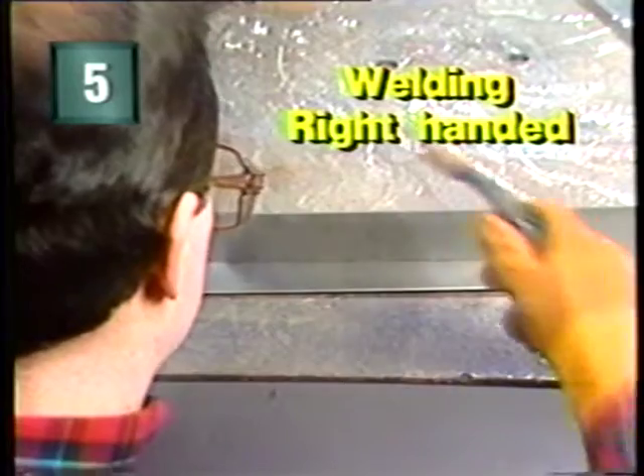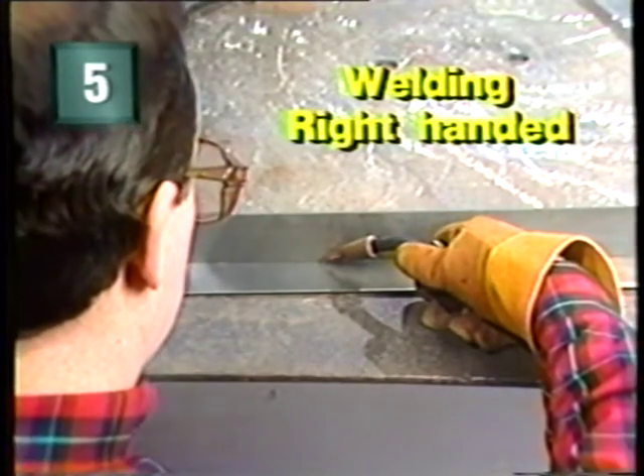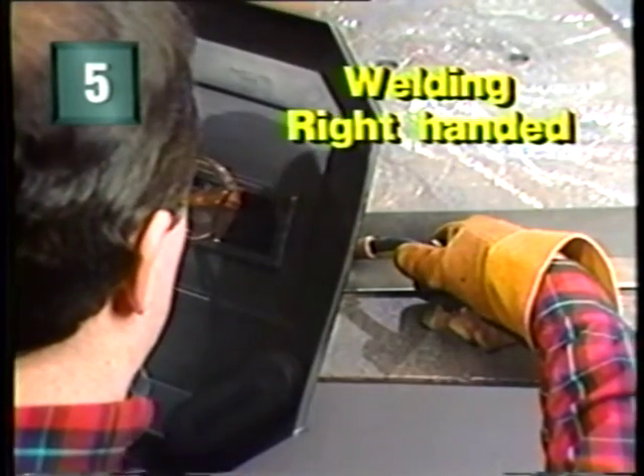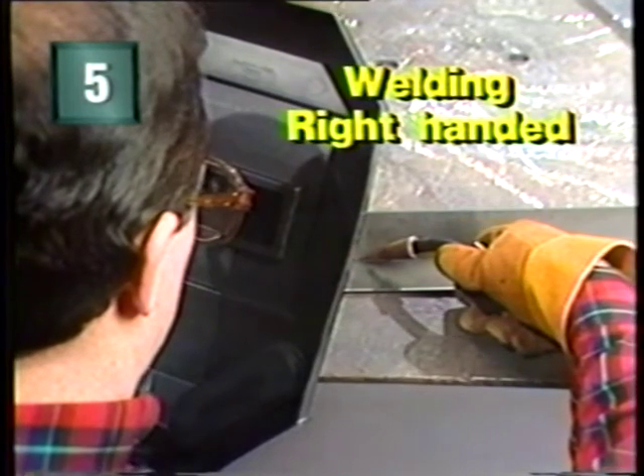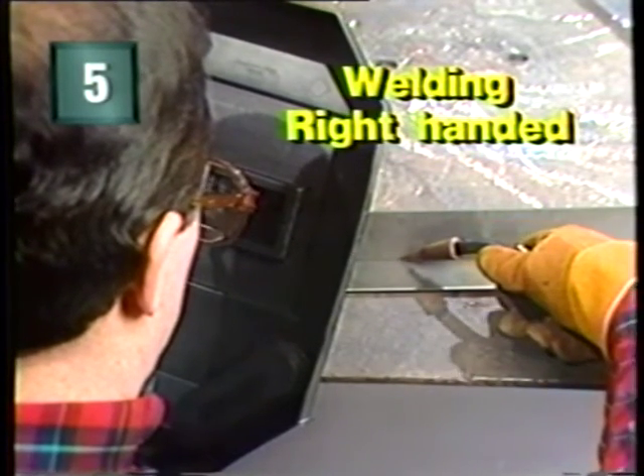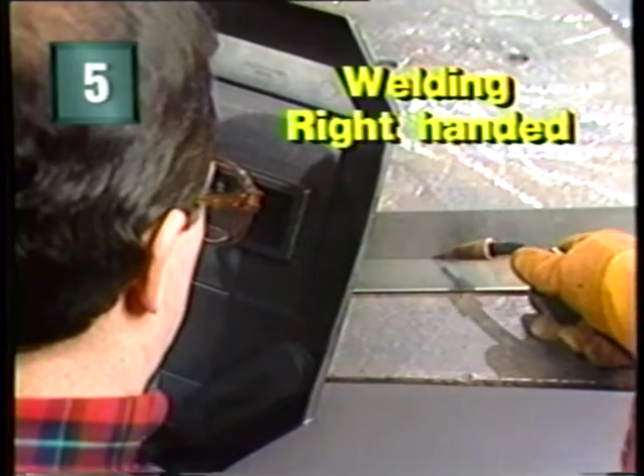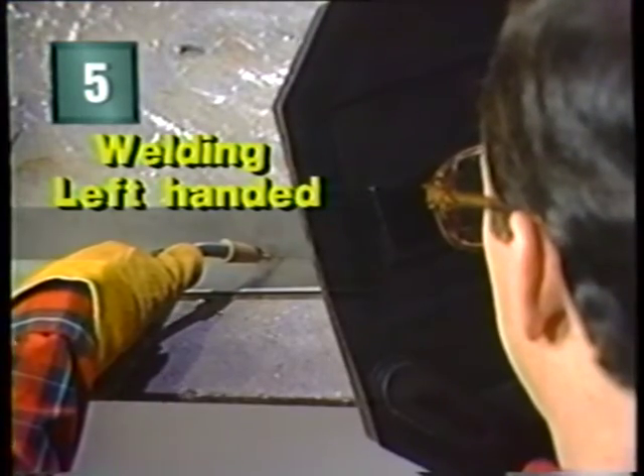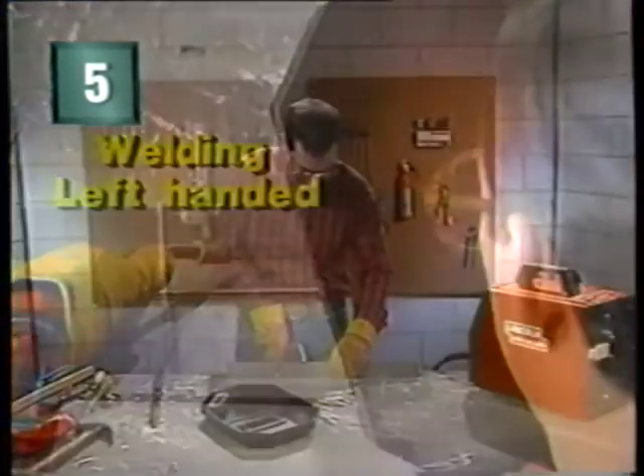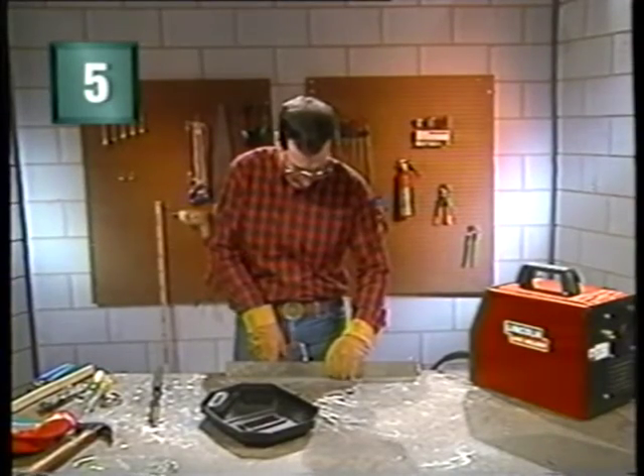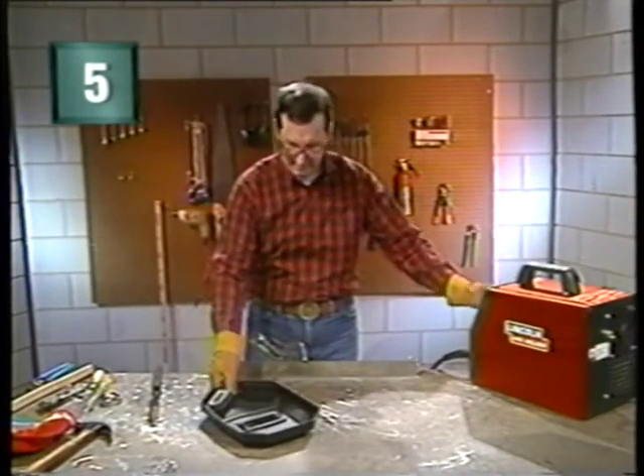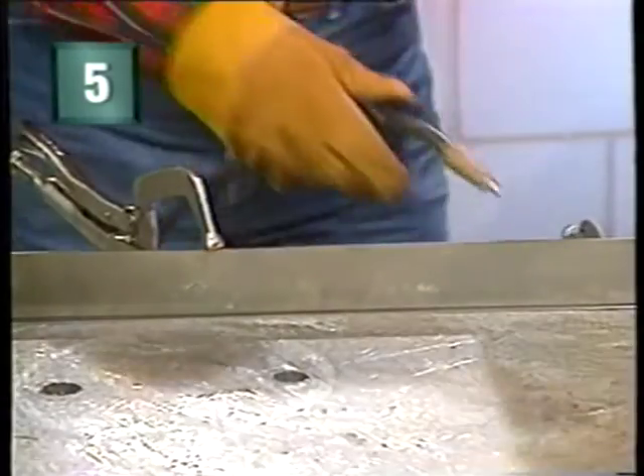If you are right-handed, hold the gun in your right hand and the hand shield in your left. Weld left to right, tilting the gun in the direction of travel. This enables you to clearly see what you are doing. Left-handers simply need to do the opposite. If possible, clamp the work pieces together. Then turn on the machine, squeeze the gun trigger, and tack the material in position to make an open corner weld. To minimize distortion, place tack welds 3 inches apart.